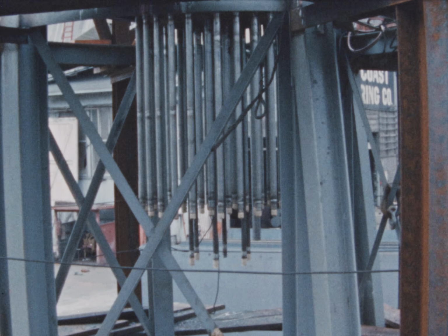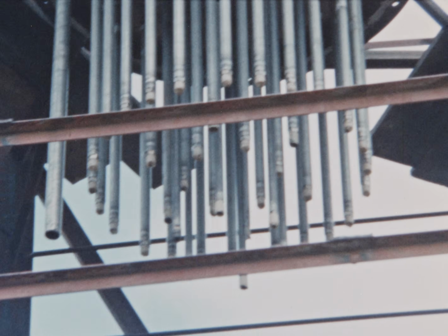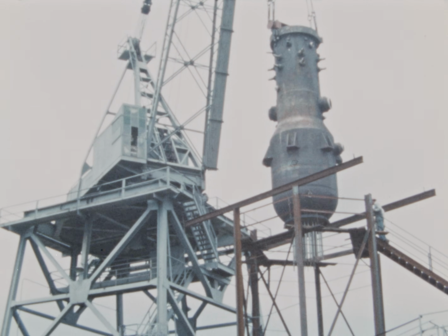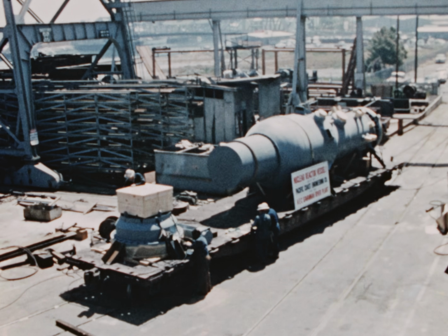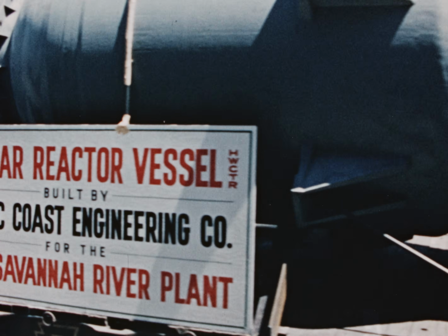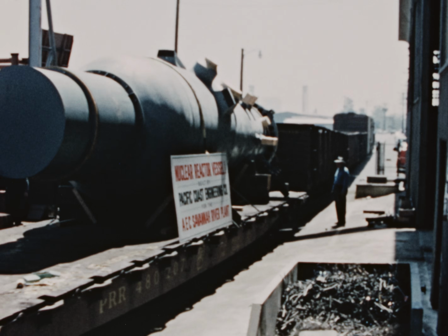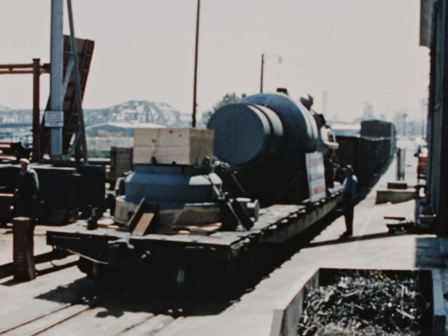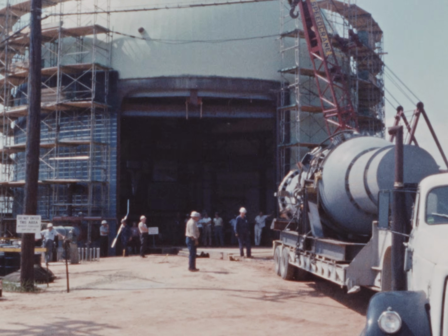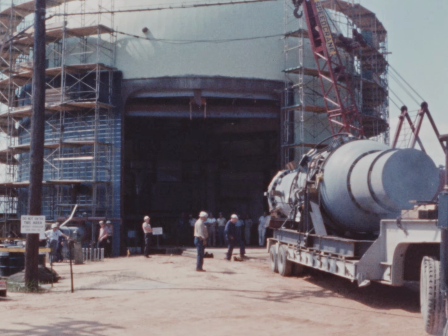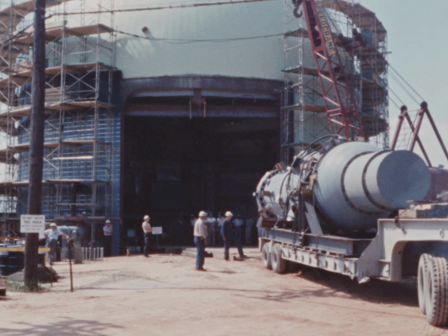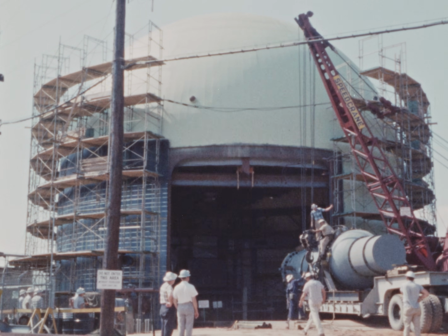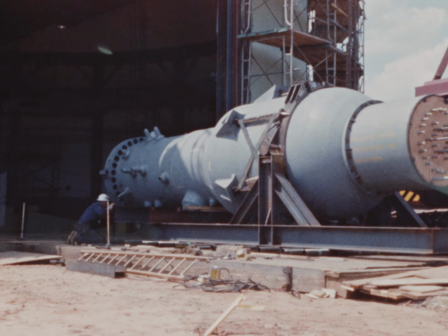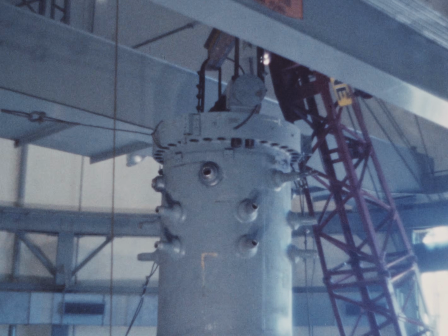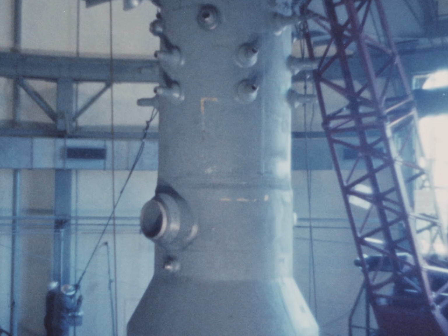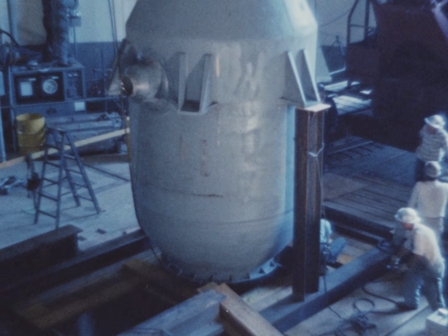The vessel, manufactured in accordance with the Unfired Pressure Vessel Code of the American Society of Mechanical Engineers, is designed to withstand pressures of 1,500 pounds per square inch at a temperature of 600 degrees Fahrenheit. The vessel was shipped to the site by rail. It was installed in the reactor building through the large construction opening. The reactor biological shield has a minimum of 11 feet of concrete between the reactor and personnel areas of the building.